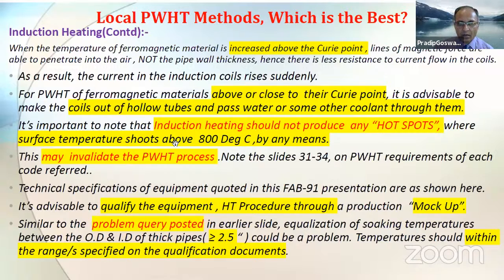But what may happen is that if this alloy, by any chance, needs to be heated to 800 degrees centigrade and above, there may be a possibility of formation of something called hot spots. And that may cause invalidation of the post-weld heat treatment process. So one has to keep that in mind.